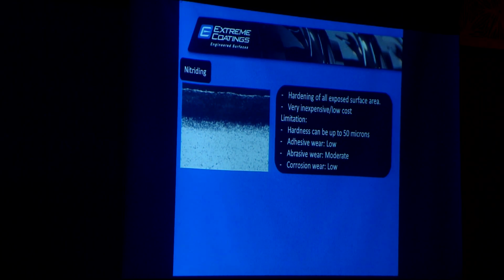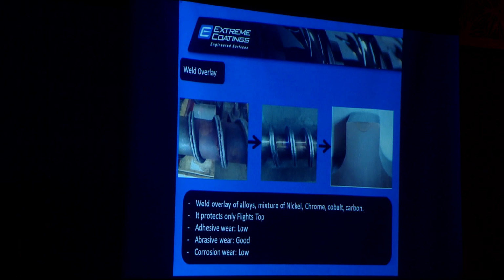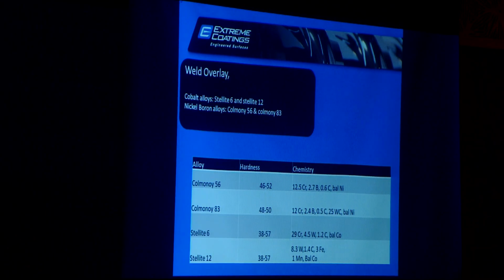The problem with this technology is that for the first 2 to 3 months, the screw will work properly. Once the hard layer is worn out, suddenly the soft screw is exposed, and there is a sudden reduction in your output. The third type is weld overlay. What people do is, you have a screw, they make a groove on the flight, and then they use welding material to fill that particular groove. And there are various grades available for this. And this is nothing but the bimetallic which you are purchasing globally. And that's why there is some confusion.